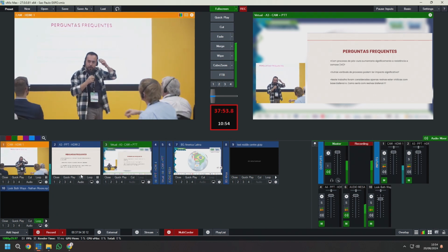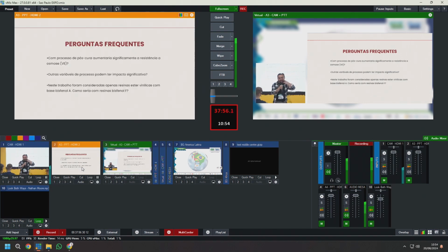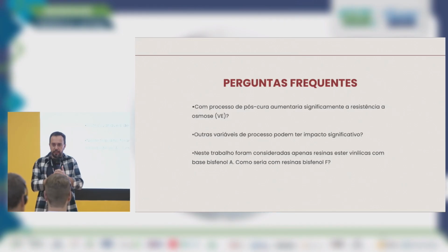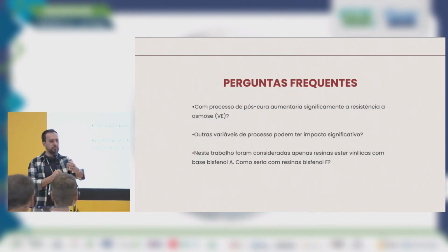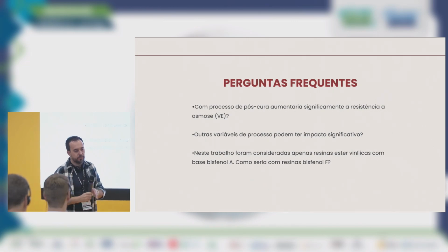And what about the vinyl ester? What, for example, what catalyst, what starter did you use? It's a good question. Everything was the same starter, Butanox 150, 1.5%, even with the vinyl ester. That's why the vinyl ester resisted just as much as the isophthalic. Another interesting point, thank you for that, could be that the starter was one of the variables.